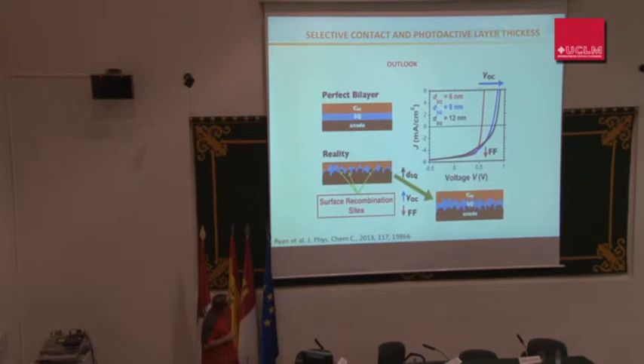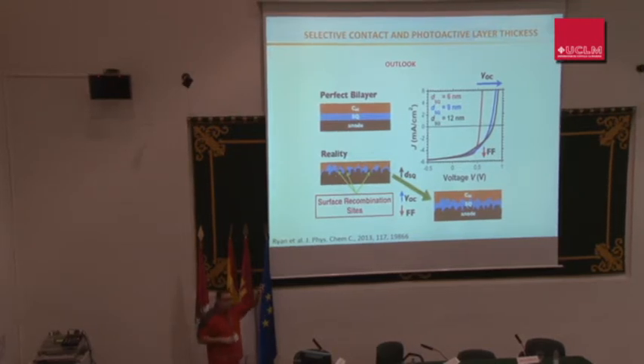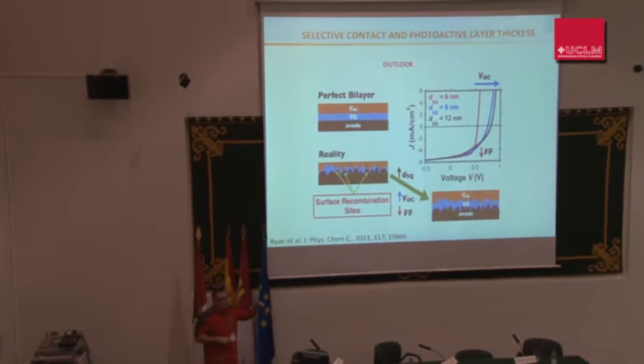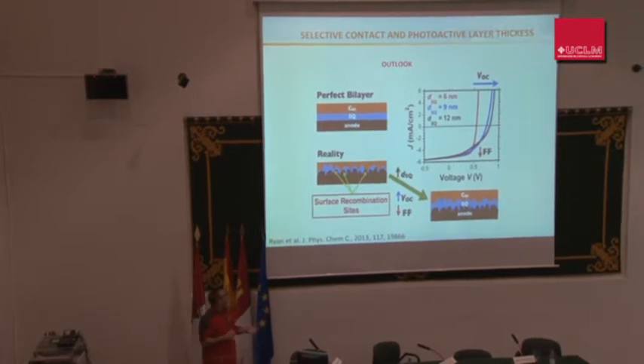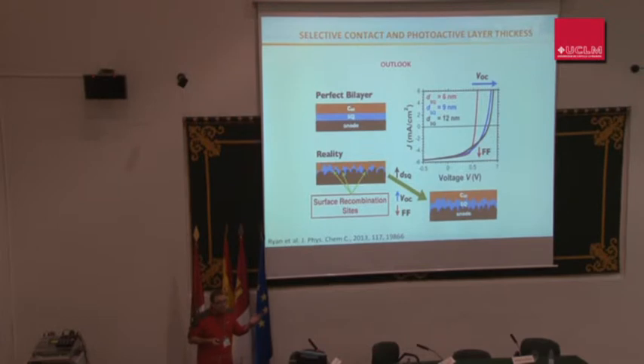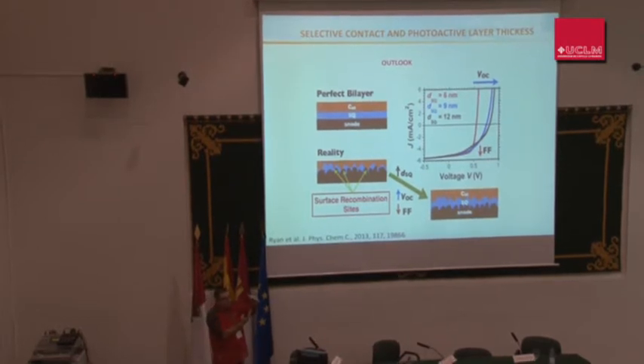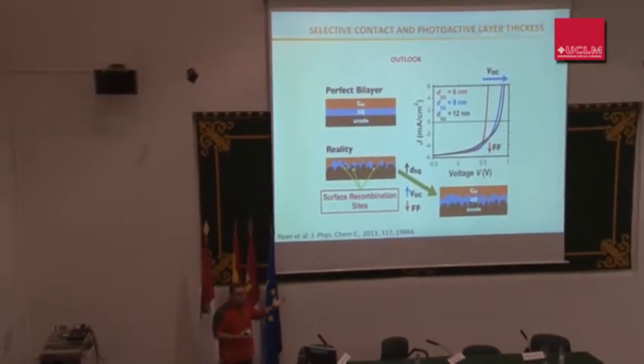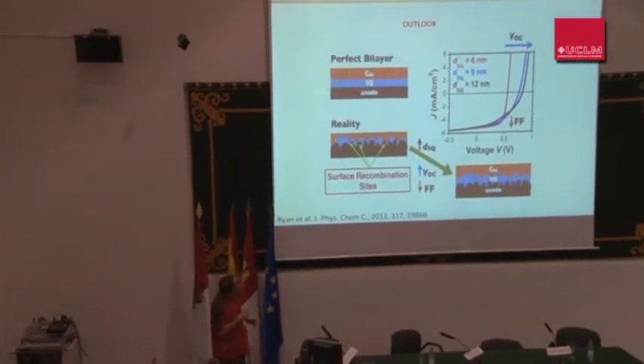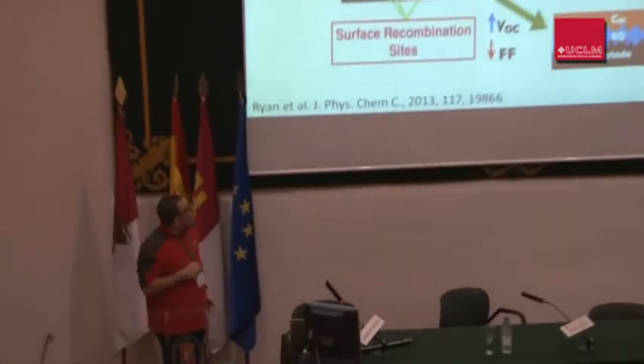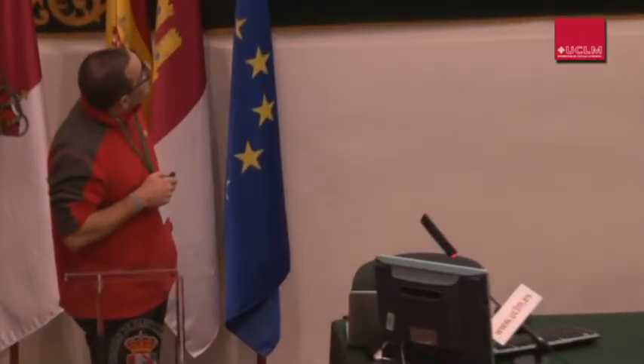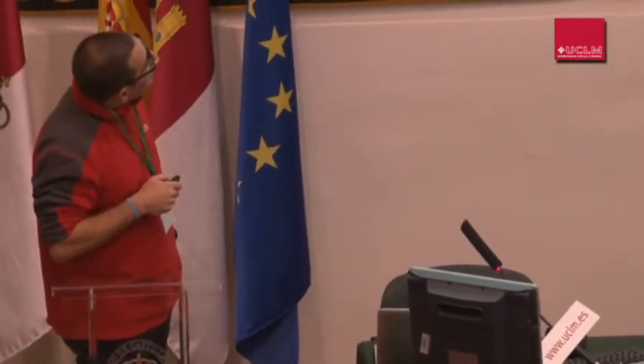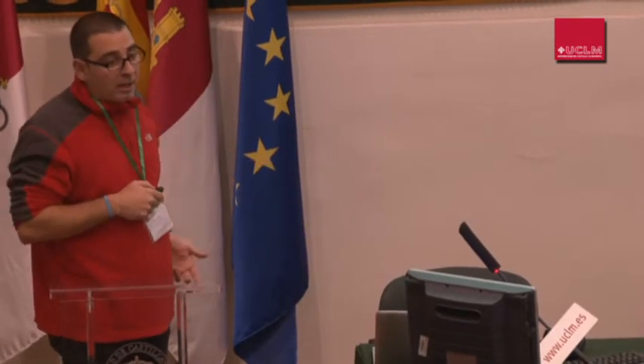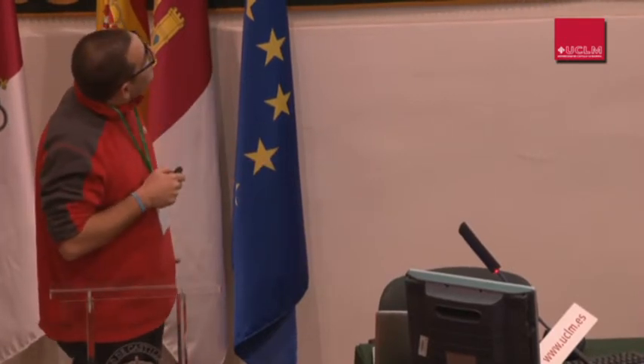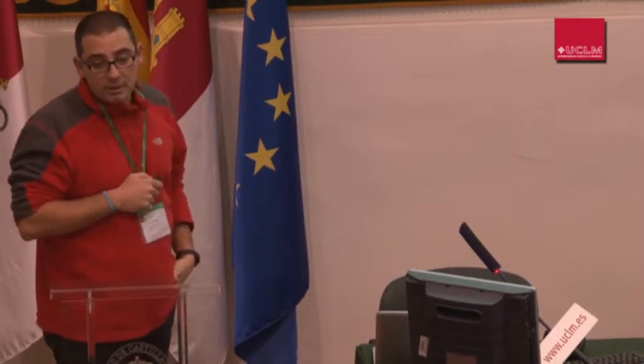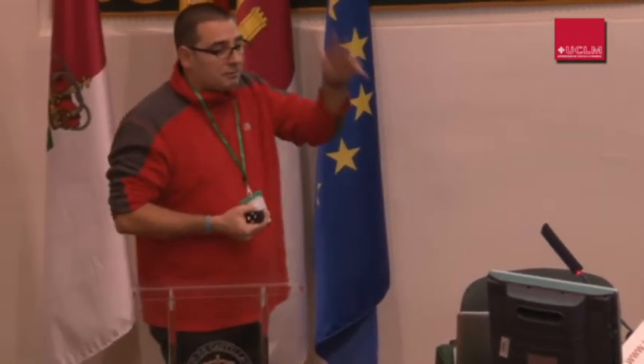The reality is that the ITO has a roughness, which is a lot. And you can ask, how much is a lot? A lot means nanometers. But your film thickness is only 20 nanometers. So it modulates how rough your film will be. Then when you put the C60 on top, if this layer is also thin, you may have an issue, which is that you have recombination sites. In other words, electrons in the C60 go to the wrong contact because it's too rough.